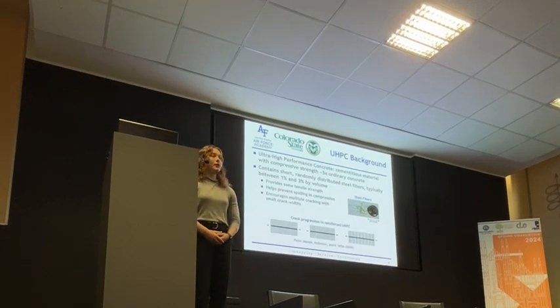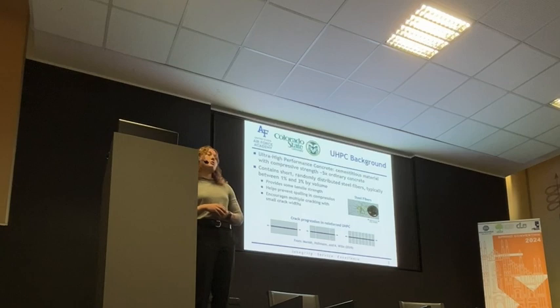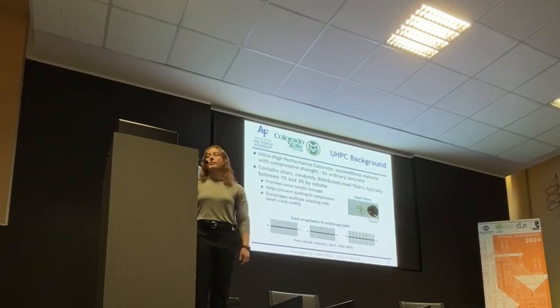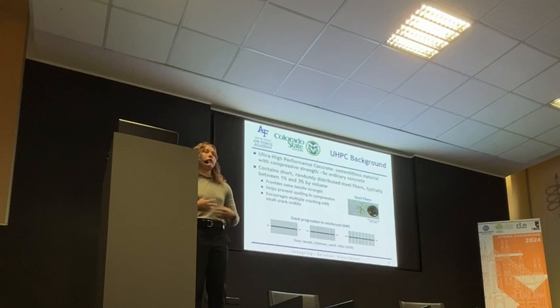And then the really unique thing about it is that it encourages multiple cracking within the specimen rather than one dominant crack forming like normal concrete normally would have. So in this figure below, you can see the crack progression that would happen in UHPC. Once cracks start to form, instead of that growing and becoming a more dominant crack, UHPC with the steel fibers facilitates smaller multiple cracks throughout the specimen, making it more durable, less permeable, and an overall more ductile material.